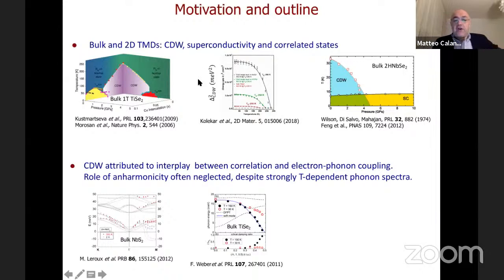On the contrary, here superconductivity is mediated by the low energy phonon modes that are the same that induce the charge density wave instability, and so there is a very strong dependence between the emergence of the charge density wave instability and superconductivity. So this is why there is this difference in the systems.